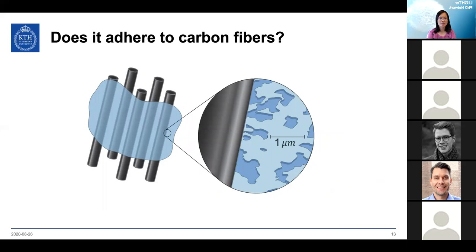The structural battery electrolyte is a porous material of solid and liquid phases. This porosity is present all the way to the surface of the carbon fibers. And this is in order to have both ion conduction to the fibers, but also adhering mechanically to them. Since the adhesive contact surface is reduced, the adhesive strength will be reduced. We would like to know how large this reduction is.